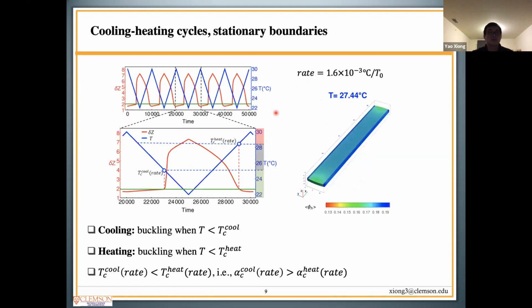We now focus on the dynamic control of patterns by introducing cooling-heating cycles. The blue line here is the temperature profile. The temperature of the sample is dynamically changed between 30 and 22 degrees Celsius. The red line here is the amplitude, and if the amplitude is above the green line, it means that the gel is buckled. During cooling, the sample remains flat until the temperature is below the critical value here, and the gel can maintain the buckling to a higher critical temperature during heating.